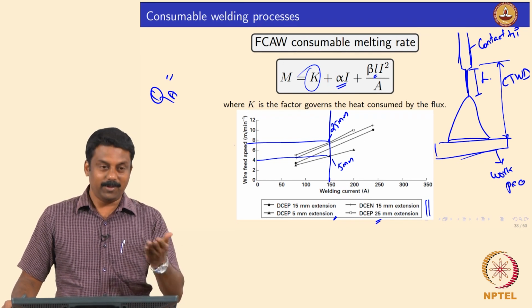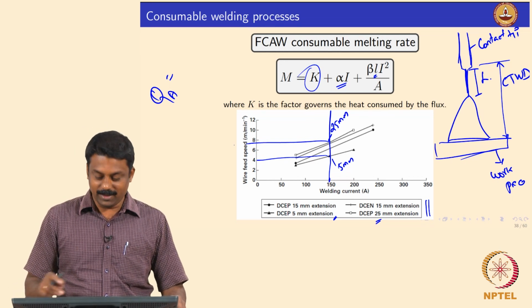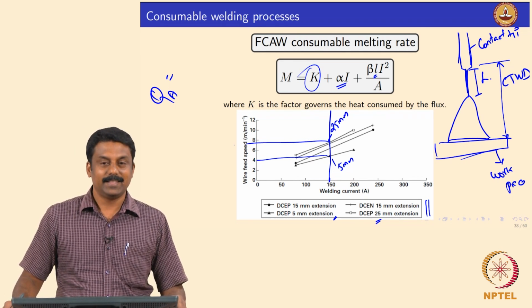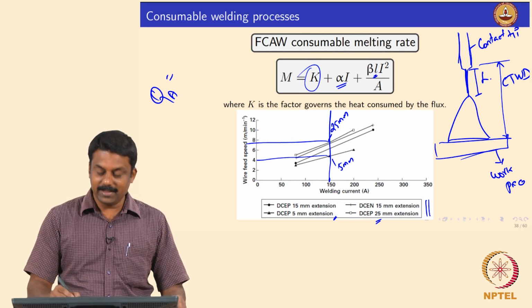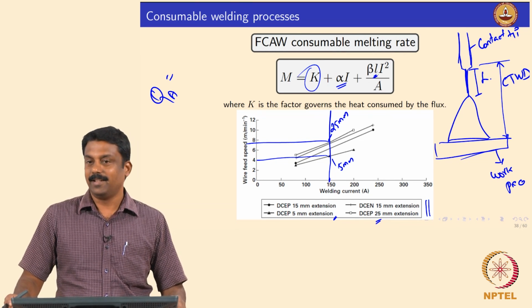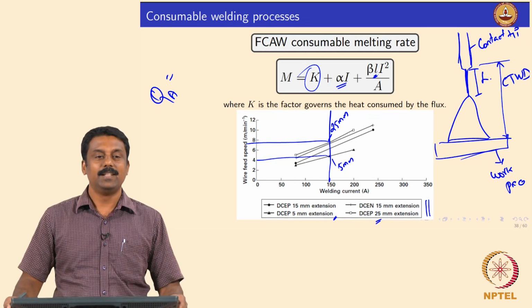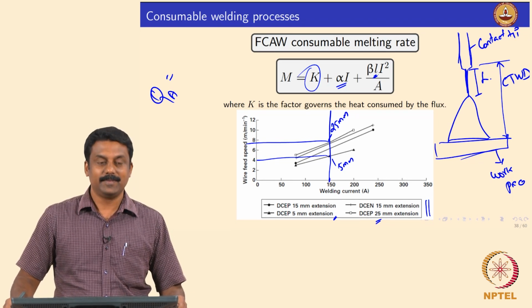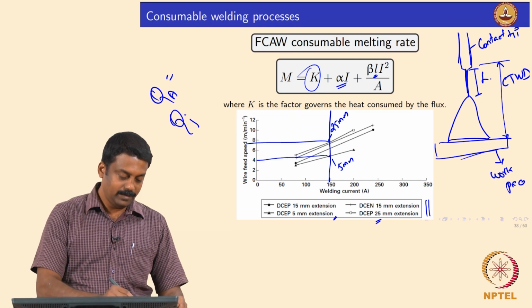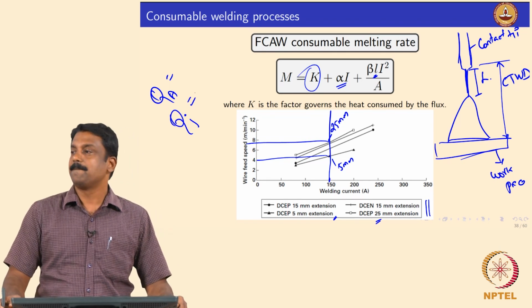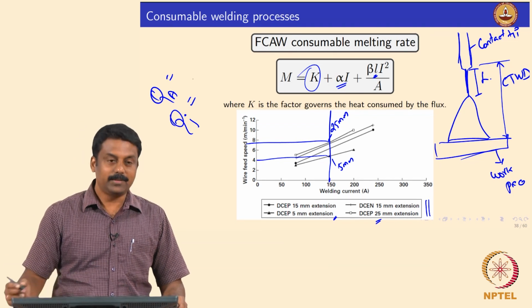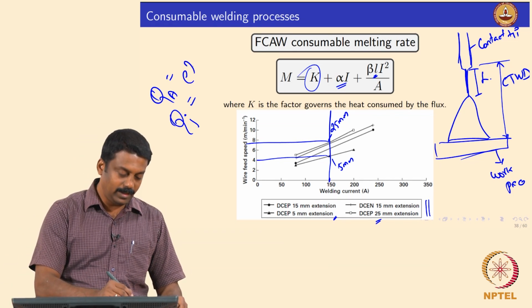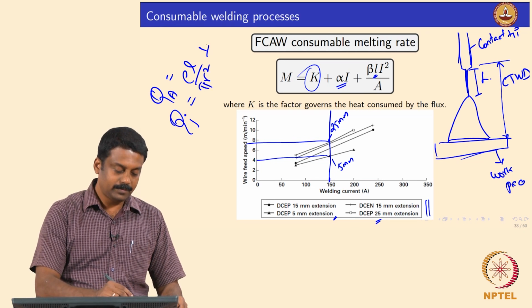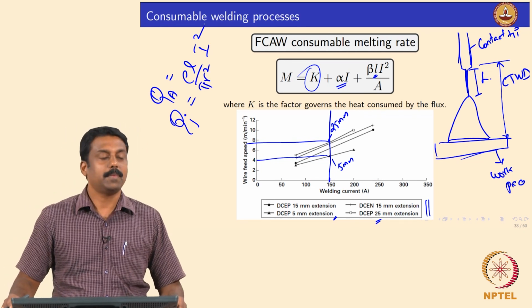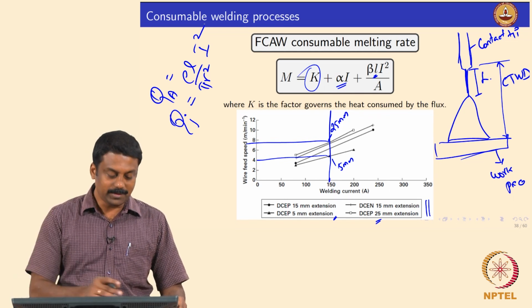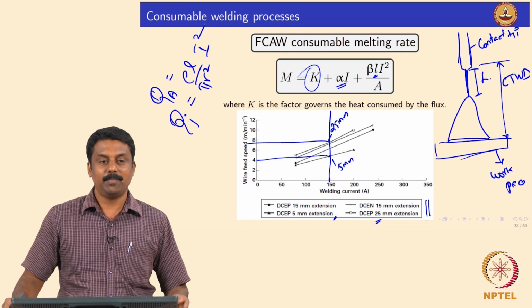See, if the current is the same, your question is why does melting rate increase? Look at this equation. If stick out length changes, melting rate increases, because the more the length, the more Joule heating. Okay, so you looked at Joule heating, right? So, what is Joule heating formula? I square R, okay, rho L by pi r square, I square, isn't it? So, that is how we derive the melting rate equation by heat balance, isn't it?